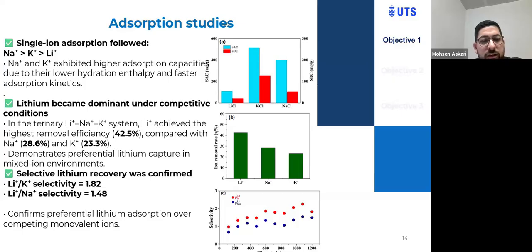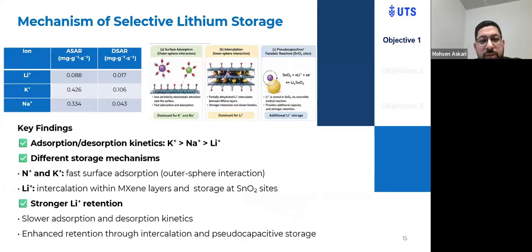In the ternary ions, we saw the lithium preference is increased, while in the single ion, we saw potassium and sodium have a higher preference than lithium. And in selectivity, lithium had a higher selectivity than potassium and sodium in a ternary solution. The reason for this mechanism was studied based on the adsorption rate and desorption rate of these three ions.